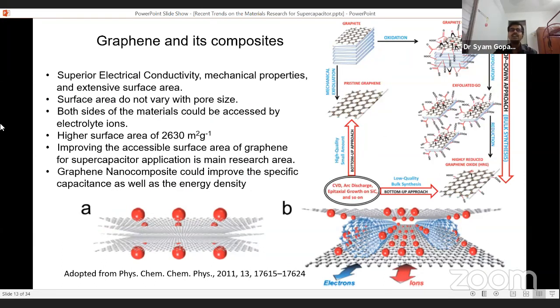Then another hot material for this particular supercapacitive realm is graphene and its composites. In graphene, we know that it's a material having a higher surface area as well as higher conductivity, and its basic problem is the accessibility of electrolyte ions to this much higher surface area. Again, the advantage of graphene is its superior electrical conductivity. Apart from that, its mechanical properties and extensive surface area. Then another advantage is that with pore size, its surface area is not changing. For energy storage applications, another added advantage is that both sides of the material can be easily accessed by electrolyte ions, then the higher surface area, as I explained earlier.